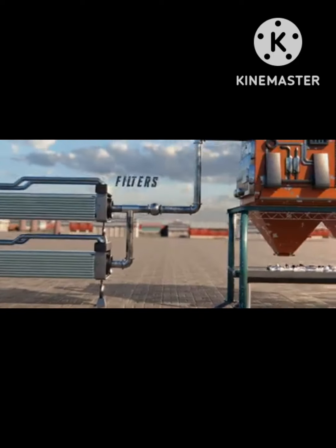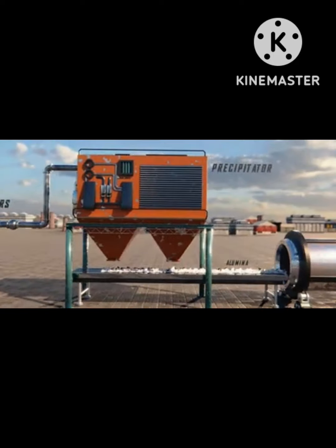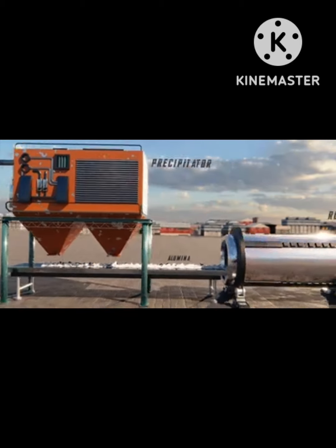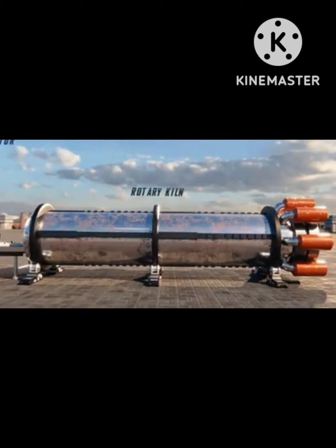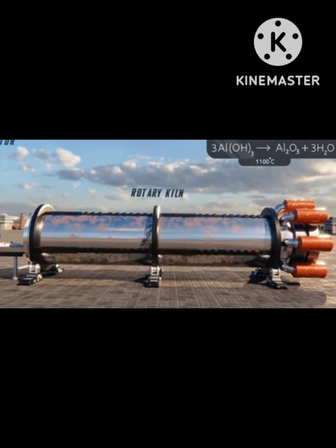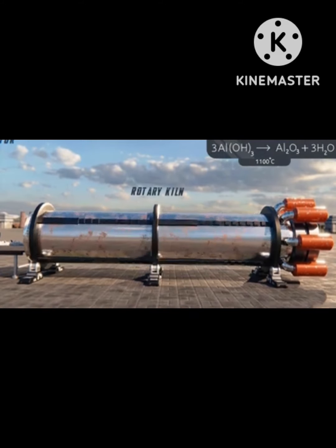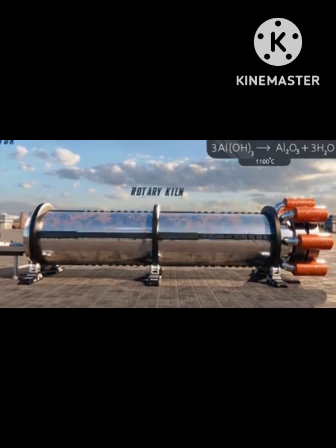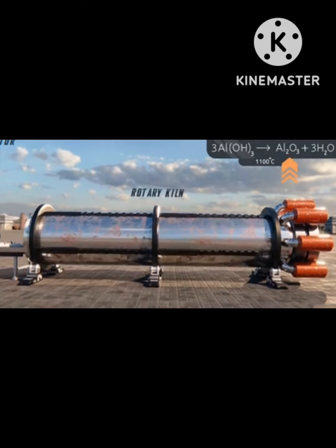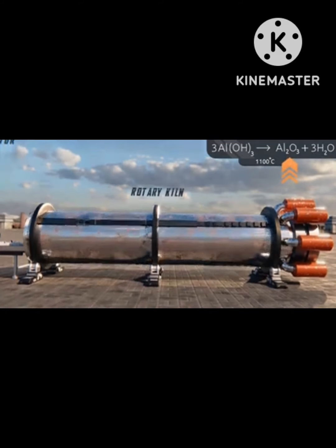Now, the sodium aluminate solution is pumped into large precipitators. Aluminium hydroxide seed crystals are added to the solution to start the precipitation process. At this point, large aluminum hydroxide crystals are formed. The crystals are then heated in rotary kilns to temperatures of 960 to 1100 degrees Celsius. This dries off the water molecules, leaving a white powder known as alumina or aluminum oxide.